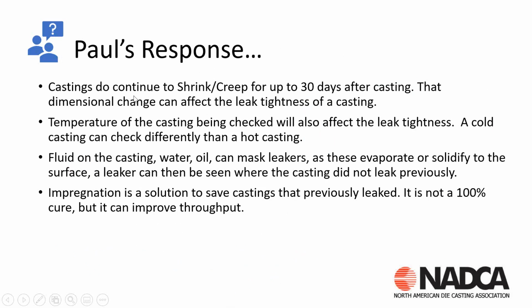So the other comment was, what over time can affect the potential leak rate? Well, castings do continue to shrink or creep, for up to 30 days. And if it was zinc, it'd be for a year. But for aluminum, typically 30 days. After that aging occurs, we do see some reduction in mass or some shrink that occurs. That could affect leakers. I wouldn't say that's probably a real path.